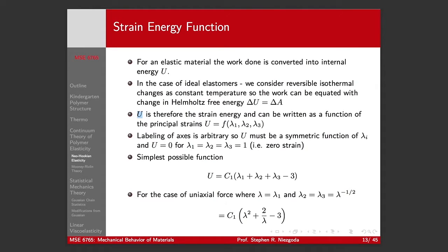And for u equals to zero, we want lambda one equals lambda two equals lambda three equals one. So, at zero strain, we should have a zero strain energy. The simplest possible case for that is just a constant times lambda one plus lambda two plus lambda three minus three. If these all equal one for strain is zero, the strain energy equals zero, and then it scales linearly with the total amount of stretch.